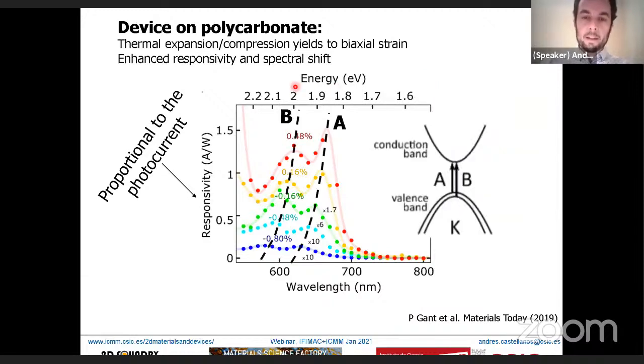The first thing we see is that these peaks shift upon straining, similar to what we saw in our previous slides on microreflectance spectroscopy. Basically, when we apply tension, we are reducing the band gap. When we apply compression, we are actually increasing the band gap. You can see how these peaks shift monotonically as a function of the strain.